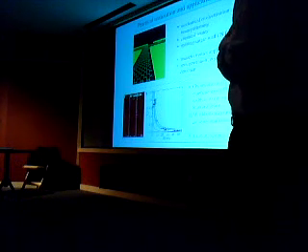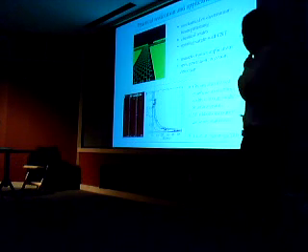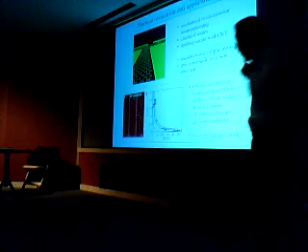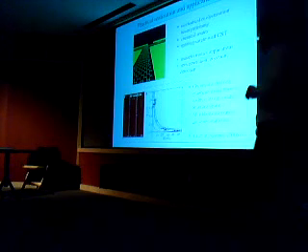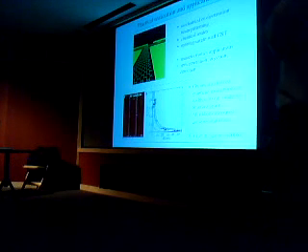graphene nanoribbons. Here I just want to show you one very recent result by Hongjie Dai's group at Stanford, where they use chemical means to make ribbons that are smaller than 10 nanometers in diameter. In fact, when they measure the gap of those ribbons, what they find is all the ribbons they make are semiconductors, and they are not able to see any metallic ribbons.